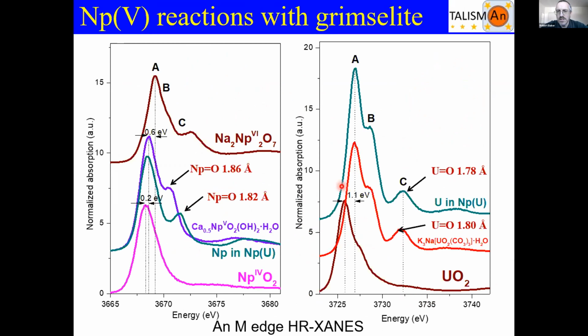Looking at the uranium first, it's certainly uranium-6, and from other work that Tonya and her group have done, we can start to get structural data from this sigma star transition. So we can get an idea of bond lengths. And this is the neptunium M-edge. So to compare with different oxidation states, it seems to fit much better for neptunium-5 than it does for 6 or 4. And again, we can start to look at bond lengths as well.